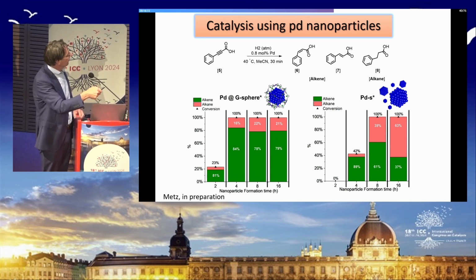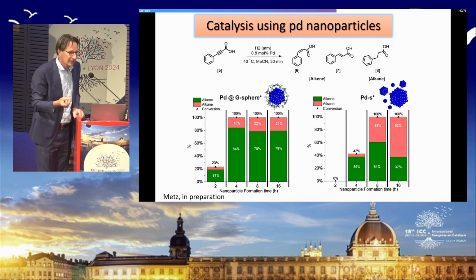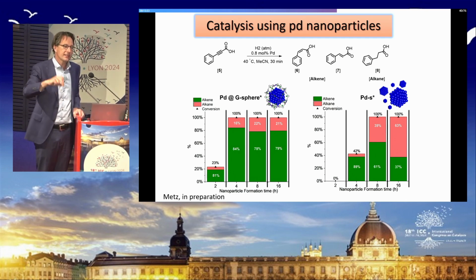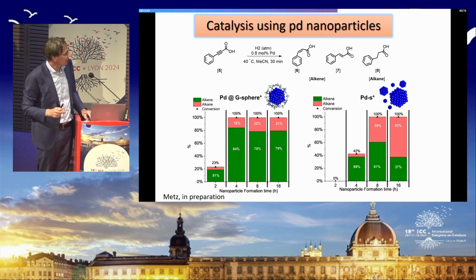And here you can see after 4 hours, we have mostly the alkene and a little bit of overhydrogenation. And the nanoparticle stays the same large size, and therefore the results are the same. If you do nanoparticle formation outside the cage, then you can see you get a lot more overhydrogenation. And again, this shows that the nanoparticle inside the cage has different properties from that outside the nanosphere.